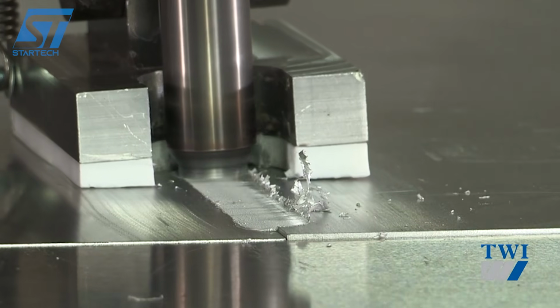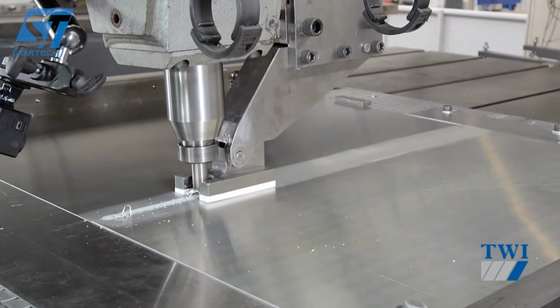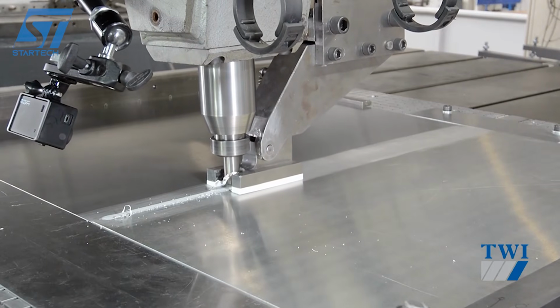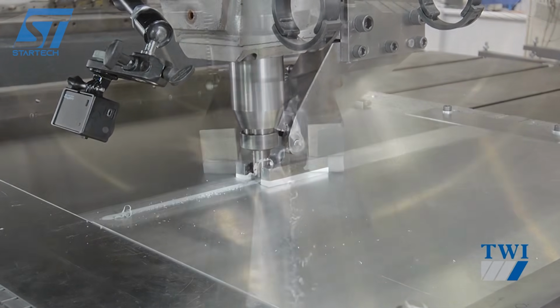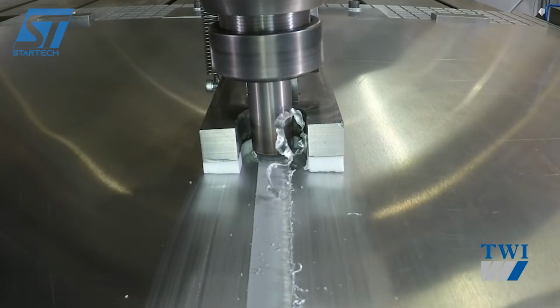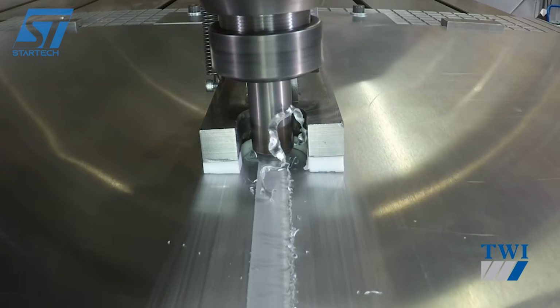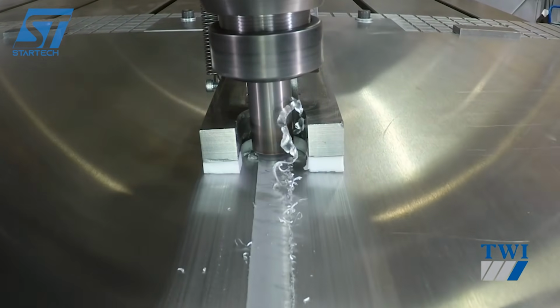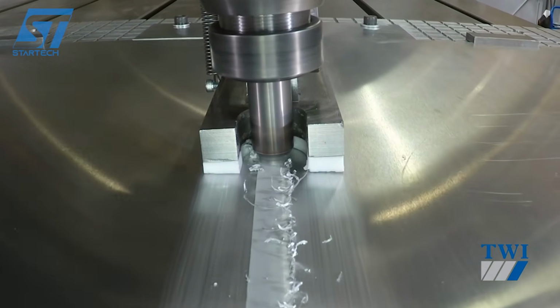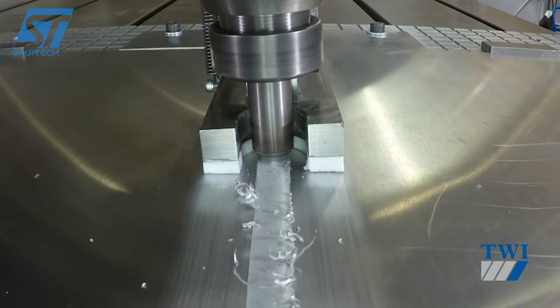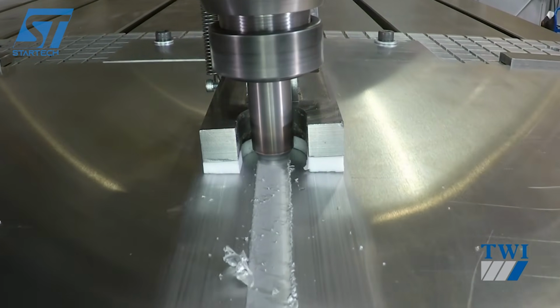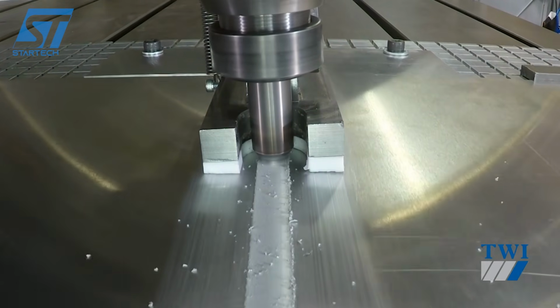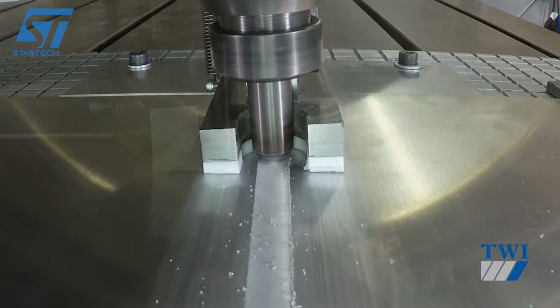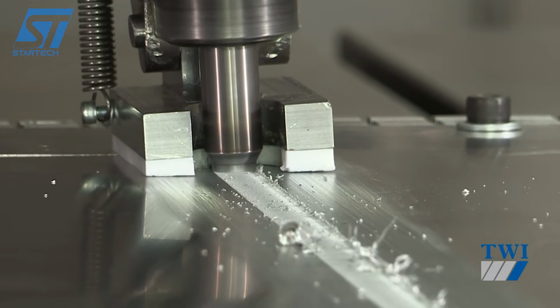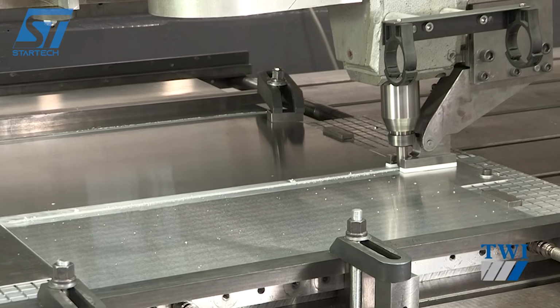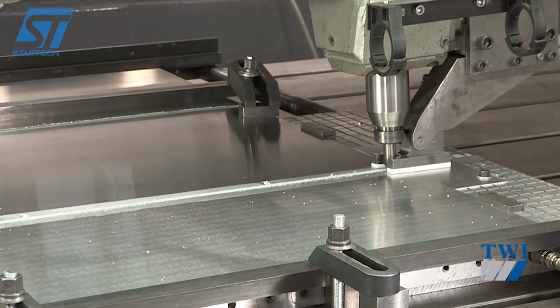In this demonstration, the optimal travel speed was found to be 1,000 millimeters per minute, fast enough for production efficiency while producing the ductility needed to survive downstream forming operations. HFQ dome forming trials confirmed that the welded blanks could withstand the high-pressure forming process without cracking at the weld line. FSW is increasingly used in aerospace, automotive lightweighting, and railcar construction, anywhere engineers need strong, lightweight aluminum joints that can handle real-world loads.